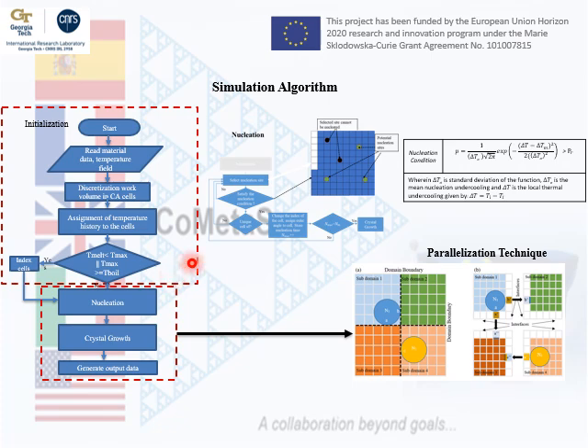Or if we desire, we can also increase the size of the simulation to consider even the fabrication of a part, right? So like an engine and so on, right? So this is not necessary, right? Because we know that in most cases the properties of the materials are contained within a certain volume. This volume corresponds to the representative volume element, which by definition is supposed to be a minimum volume. Okay, but in any case, the model is implemented in parallel, right? So we utilize transfer of information across computational domains, and this information allows a perfect coupling between the computational domains so that the errors are kept to a minimum.